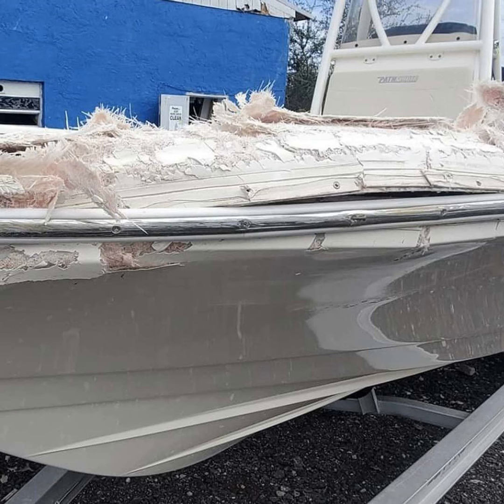You know that you can grind bad glass until you get to good glass, and then you can proceed as you were before. So now when you come out to the front side of the glass, the outside of the hole, and you start grinding, as soon as you get through the damaged fiberglass, which was the entire laminate thickness, you're now going to start grinding into the patch you just applied. And as soon as you see that you're grinding the patch, you stop. You've removed all the bad fiberglass. You've got through to the new glass.